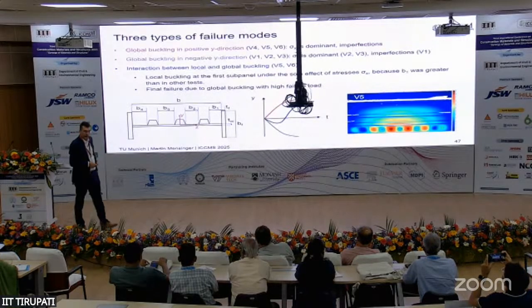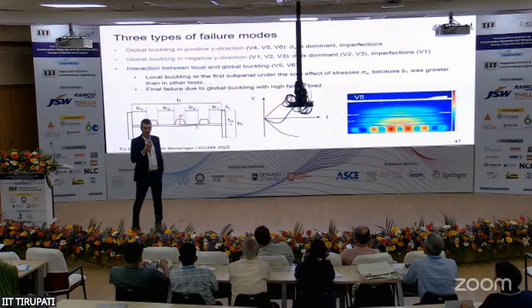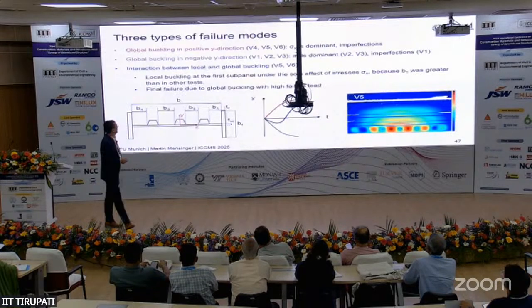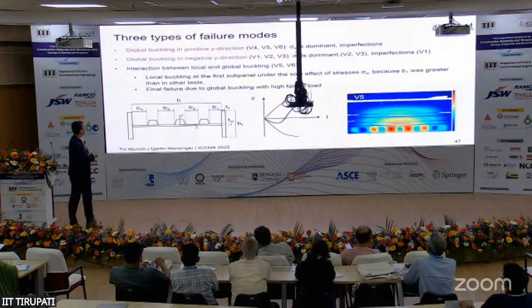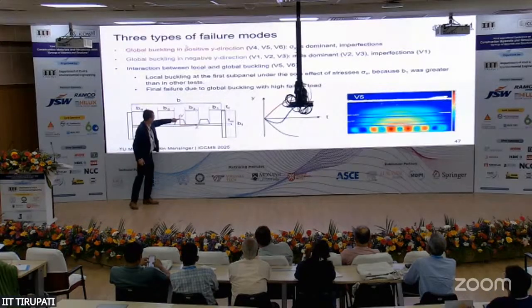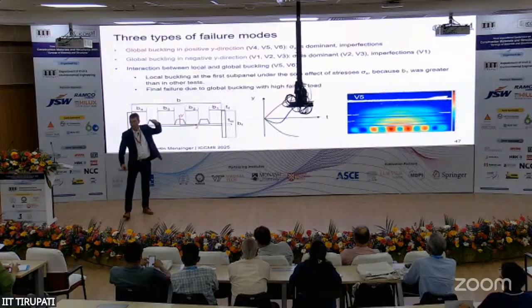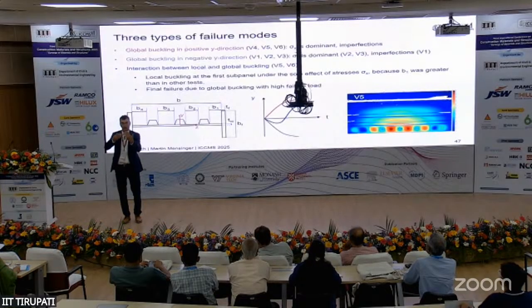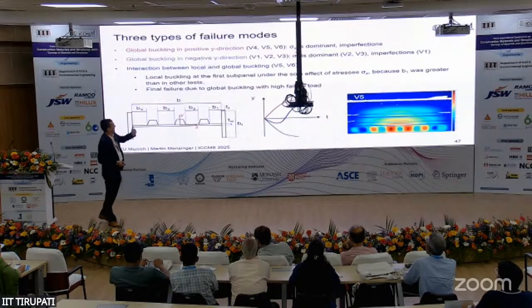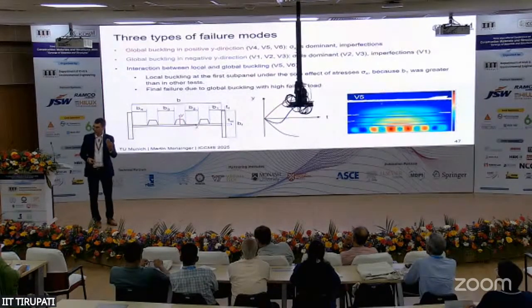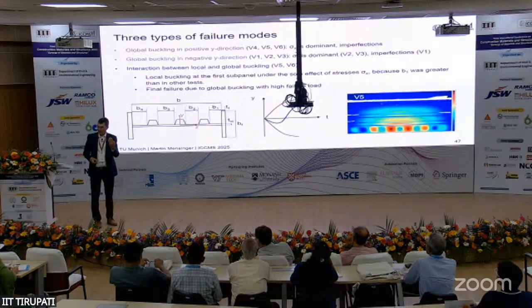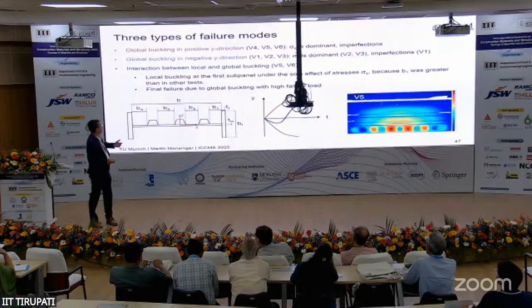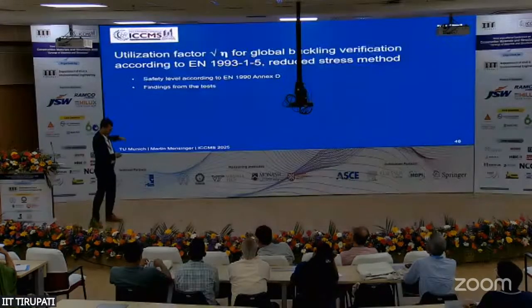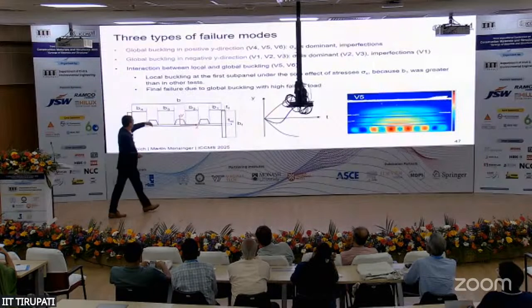And during our tests we observed 3 different failure modes. In some cases we had buckling in positive Y direction. So this is the direction up in the direction of the stiffeners. And this is the case when the longitudinal stress is dominant and the cross-directional stress is small. In case the cross-directional stress is dominant and the longitudinal stress is small, we will have a failure in negative Y direction, this direction.